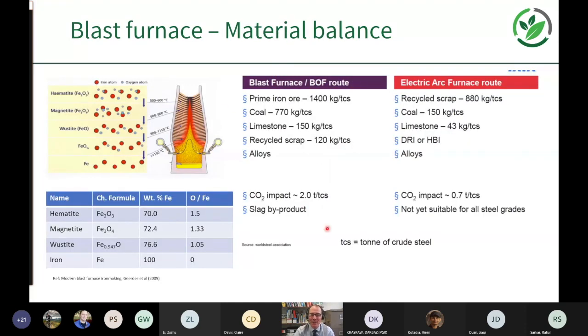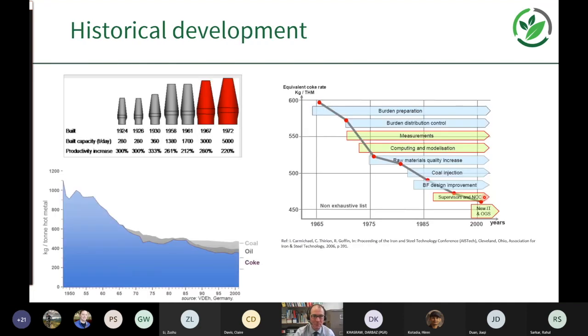And then as a material balance, for the blast furnace you're using around 2.4 tons of raw materials to produce a ton of crude steel. So it requires a lot of materials as well, compared to the electric arc furnace route, which doesn't require anywhere near the same quantity of raw materials. So historically, the improvements that we've seen have all been driven by scale, really. Blast furnaces have increased massively in size. In fact, in 2016, POSCO, the Korean steel manufacturer, started metal production using a blast furnace with an internal volume of 6,000 cubic meters, capable of an annual production of 5.65 million tons.